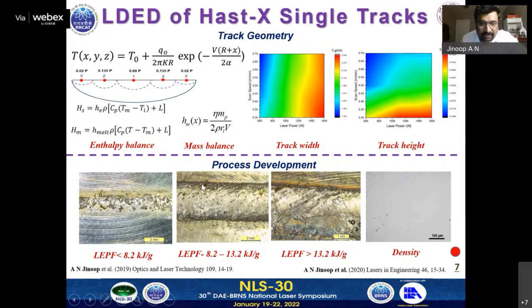It's mainly because of the higher thermal energy leading to residual stresses resulting in the cracking. So with this, we found that this is a process window where we have to work on to process the material without any defects or cracks. Further, we went into the geometrical studies and the density analysis of the samples, and we found that these samples are highly dense in nature. So we selected this range of parameters for the further studies.